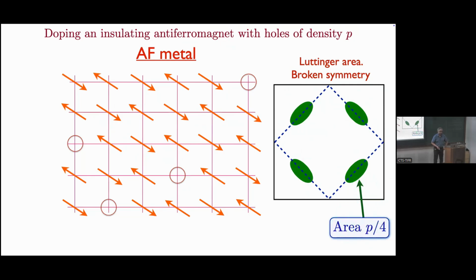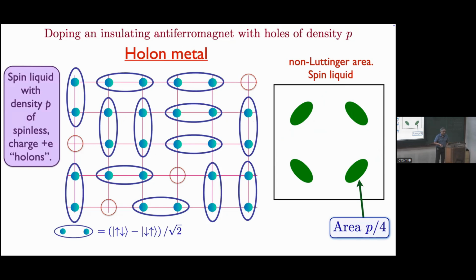So the total area should be P, and so you get P over 4, 2 for spin and 2 for valley. Okay. So the area for the antiferromagnetically ordered metal, or the thermally fluctuating metal, because thermal fluctuations don't change the apparent area of the Fermi surface, should be P over 4. And you do see this in the ordered antiferromagnet. You go to very low doping, it's beautifully seen, pockets of area P over 4.